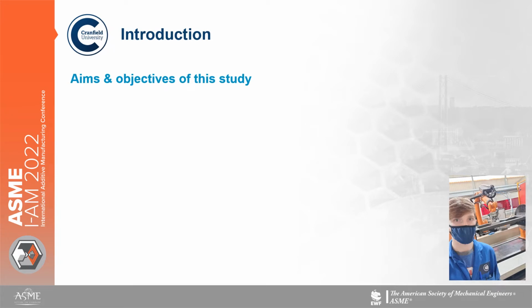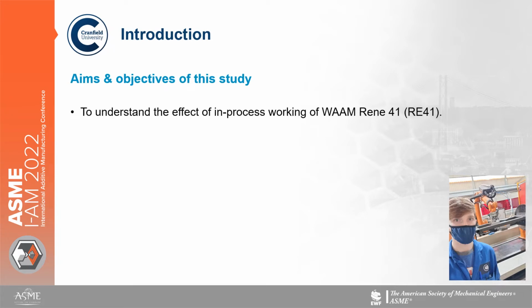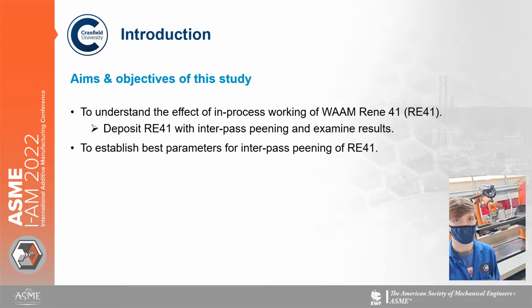So the aims and objectives of this study are to understand the effect of in-process working on wire plus arc additive manufactured Rene 41. So to do that, we deposited Rene 41 using interpass peening, and we examined the results. We also wanted to establish best parameters for interpass peening of Rene 41. And to do that, we trialed the peening using 3 different parameters.